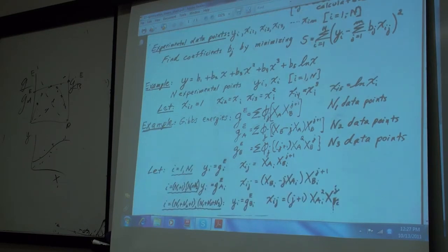You're minimizing the sum of squares. So you can then put all your data points into one optimization routine. You put in all n1 plus n2 plus n3 data points, identifying which ones are GXS, which ones are GXSA, which ones are GXSB, and you say go to it. It minimizes the sum of squares and gives you the phis that give you the best fit.